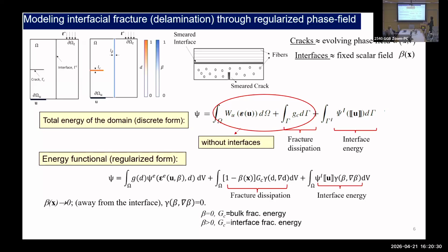Okay. And because this damage is happening at the expense of stored elastic energy, as the damage propagates, you lose the stored elastic energy. That is taken care of by this so-called degradation function, g(d), sitting on this elastic energy term, right? So as d increases, g(d) decreases, and your elastic strain energy, the stored elastic energy, keeps dropping. So the material loses stiffness. And in the interface regularization, just pay attention that we have a very similar regularization term, just like the damage one I showed you before, okay, which depends on beta as well as the gradient of beta. Okay. Now, the introduction of this gradient term in both cases makes this method, the phase field method, non-local. So it doesn't depend on the mesh. Okay.